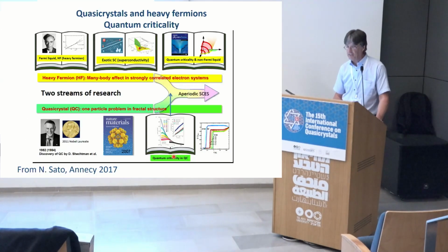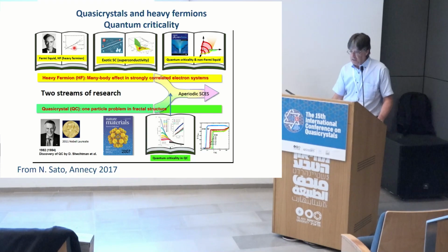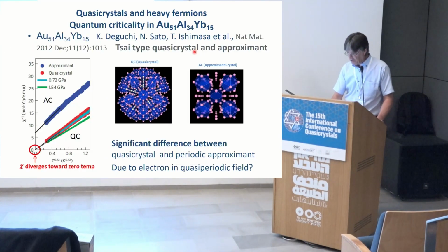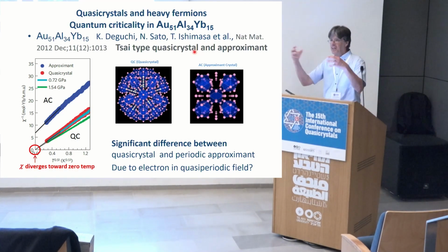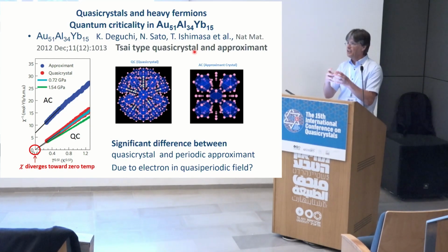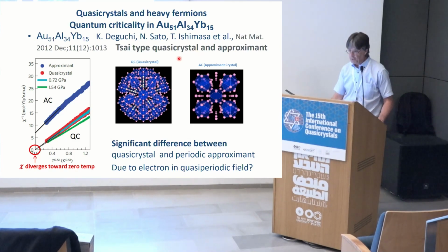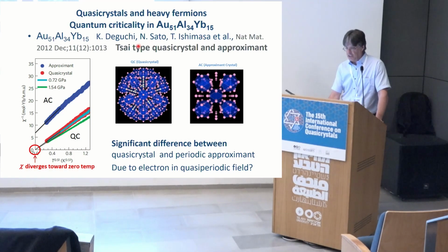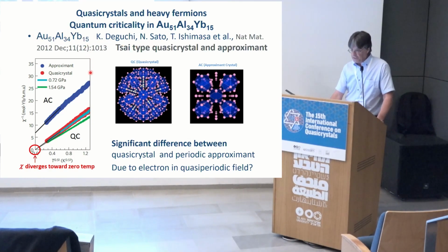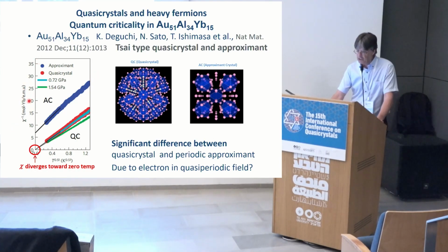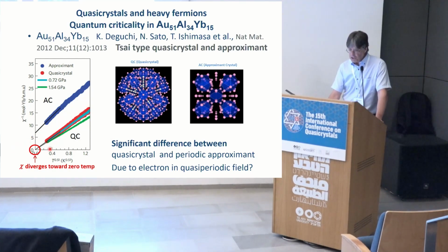Unfortunately, experimentally, this is very difficult to analyze. And there is maybe one recent work where it has been emphasized, although it's still a matter of debate. This is the community working on heavy fermions. So heavy fermions, it's another word for heavy electrons. Electrons are not heavy, but in some specific systems, there are correlations between electrons which make them behave as if they had a large mass. And what the group of Deguchi, Sato and Ishimasa in Japan have discovered in this gold, aluminum, ytterbium quasicrystal is that if they cool down the system and look at the magnetic susceptibility, they have a very different behavior, which could be related to the fact that we have this hierarchical electronic wave function on the quasicrystal, although it's not yet proven.